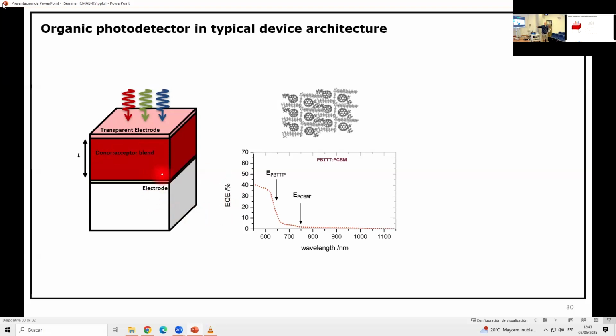So the typical device for an OLED, again, solar cell, you have your absorber or emitter. Let's stay with an absorber. I didn't draw the P and N layers in this case. And you have a transparent electrode because the light needs to reach this layer. Usually this is a reflecting electrode, so you can pass 2 times. And I chose here a donor acceptor blend, which we liked a lot as a model system because it makes these nice mixed crystals. So we know more or less what happens on the morphological scale. The polymer here is PBTTT. The fullerene doesn't absorb much.